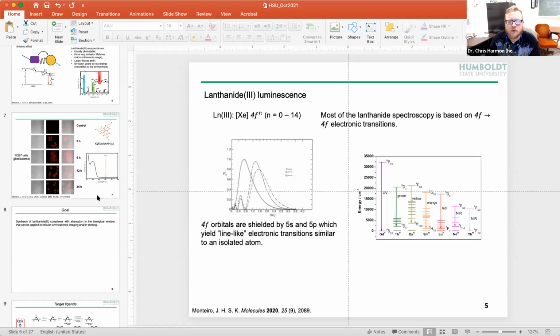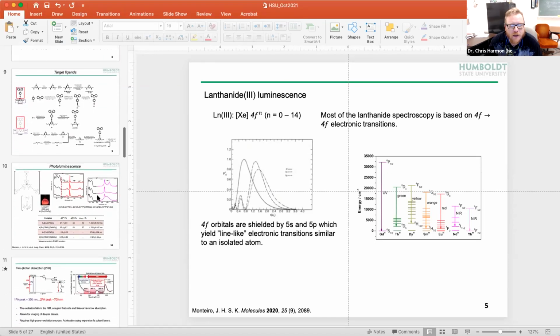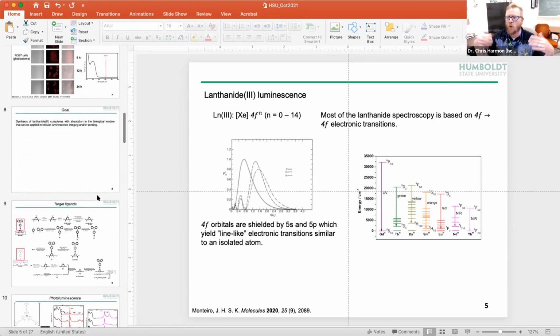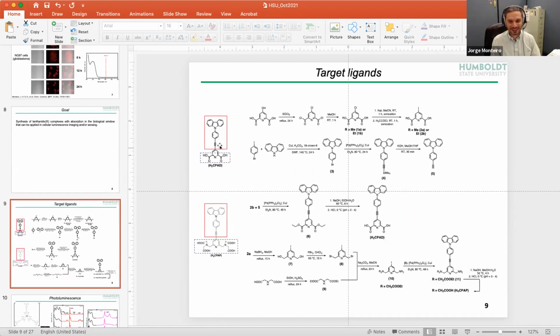Jorge, is it oversimplified to think of that as the classic particle in the box, like what happens with quantum dots, the bigger the system gets, the more red shifted it becomes? Exactly that, Chris. Exactly. If you don't have the carbazole, the length is going to be all the way here. When you add the carbazole, you increase the length of the box, and that decreases the energy of the transition.